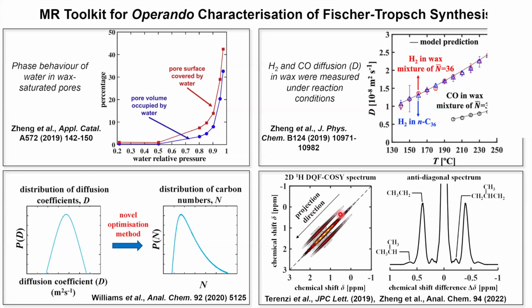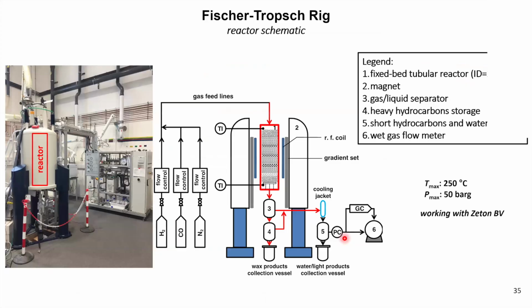Just by doing a projection down here, we can extract information about chain lengths, because we see end chains, but also you see peaks for different types of branching as well. Anyway, that is some of the background work that we did before looking at the actual reaction.